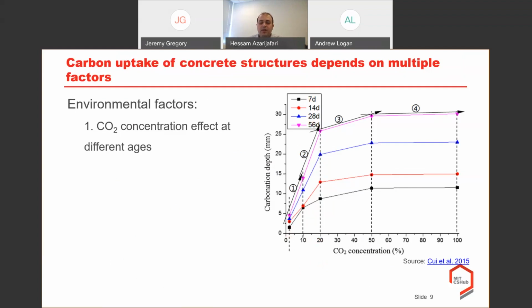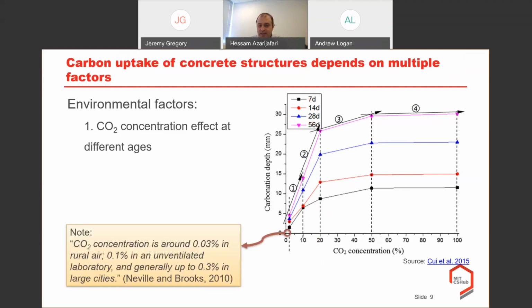What I would like to emphasize here is that in our real case, the CO2 concentration is quite different from the experimental lab setups. More importantly, in rural neighborhoods and rural areas, the CO2 concentration is very close to 0.03%, as opposed to a lab condition that can be up to 0.1%, or in a metropolitan area or large cities, it can be up to 0.3%.